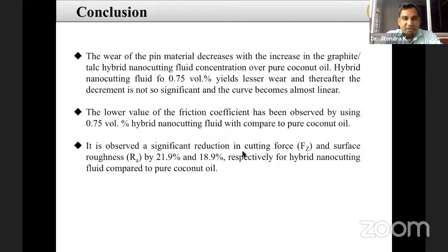Another work, so conclusion from this work, whatever I have already shown, told you that in case of cutting forces, we observed that if we use the nano cutting fluid rather than the pure coconut oil, a significant reduction in the force and surface roughness, respectively 22% and 19%, from the hybrid nano cutting fluid compared to the pure coconut oil. And 0.75 volume percentage of hybrid nano cutting fluid shows the better output parameters. Just observe it, like surface roughness and cutting forces. These are the few things.